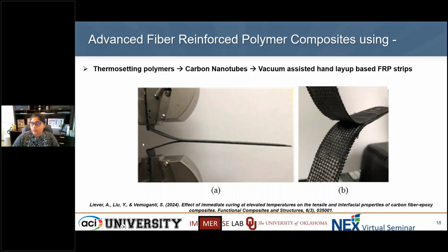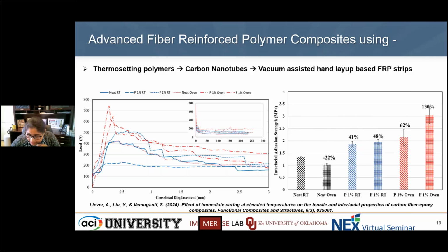By pulling that one end, we basically understand how much force is needed to pull one layer of the fabric from the other. So if we see in that context, depending on different percentages of carbon nanotubes and also curing temperatures, we saw that a functionalized carbon nanotube made polymeric resin for vacuum-based layup can increase the adhesion by 130%. The interfacial adhesion strength, which is also referred to as the peel strength, increased by 130% when you compare it to a non-nano-modified polymeric resin. So that FRP strips were very important to understand how peel strength can be affected.